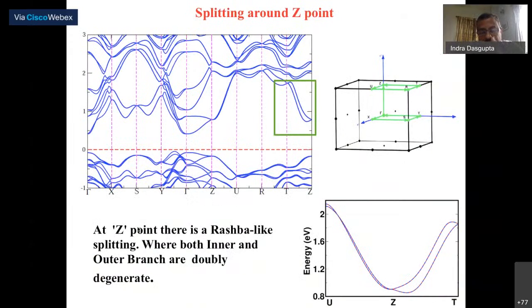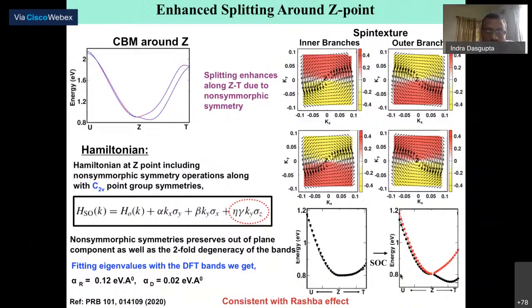I'll just touch upon another point in the k-space, the Z point, where the non-symmorphic symmetry operations are much more effective, and which gives rise to a larger splitting. One can model this, and that's precisely what we have done. Here, again, you have a Rashba effect, but now this Rashba effect has a kz component. It's not only confined to the x-y plane, which tells us that this non-symmorphic operation orients the Rashba spin texture in such a way that it picks up this kz component, which you can model by bringing an additional term into your model Hamiltonian.